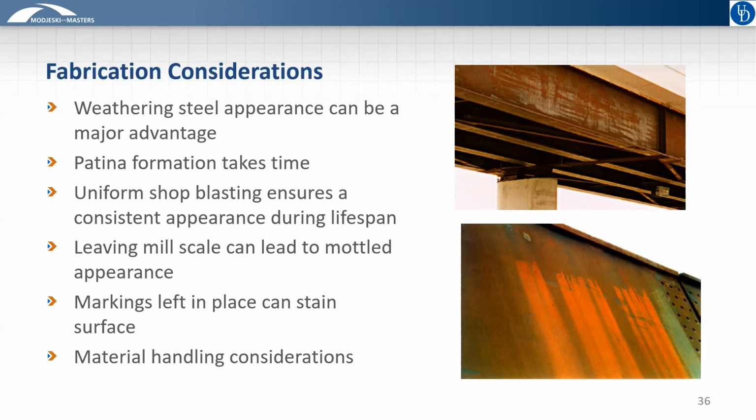And it will perform well if you leave the mill scale on, but it does tend to cause the weathering steel to have a very mottled appearance during the early stages of the patina, and it really takes a long time before it becomes more uniform. So the recommendation is to shot blast the girders and remove the mill scale so that you get a more uniform patina formation and much improved aesthetics.